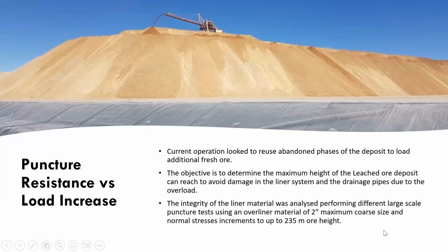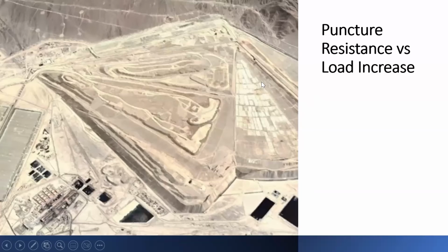The integrity of the liner material was analyzed, performing different large-scale testing using the overliner material of 2 inches maximum coarse size in this case, and normal stress increments up to 235 meters of height. In this aerial view, we have the deposit and the operation that are starting to put additional layers of the leach ore here.